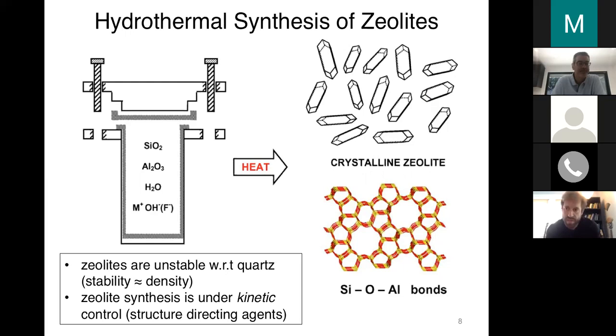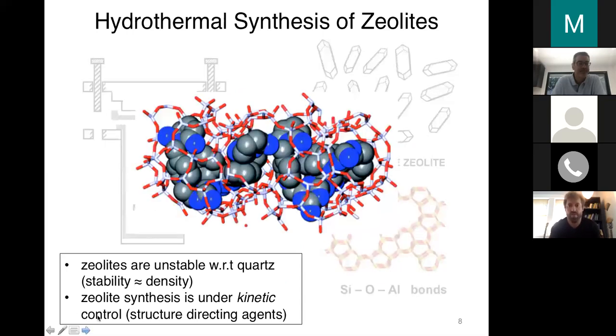Now, because zeolites have this large amount of internal pore volume, their density is less than quartz. And because of that, they're less thermodynamically stable than quartz, which means that these synthetic conditions typically have to be under some sort of kinetic control in order to get these thermodynamically less stable polymorphs of SiO2. And one of the ways that this is accomplished is by adding organic molecules known as structure directing agents to the synthesis gel inside the Parr bomb. And what this does is it creates a kind of organic scaffold around which the zeolite lattice will self-assemble. And that's how you can get these really elaborate, complicated core architectures inside of these materials.